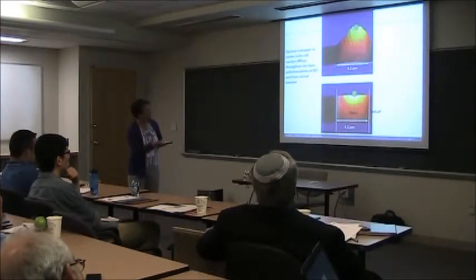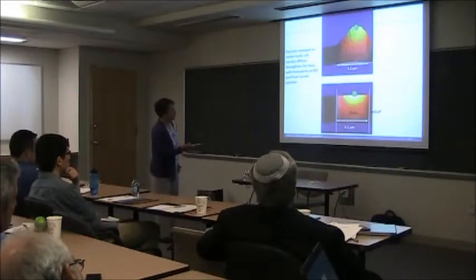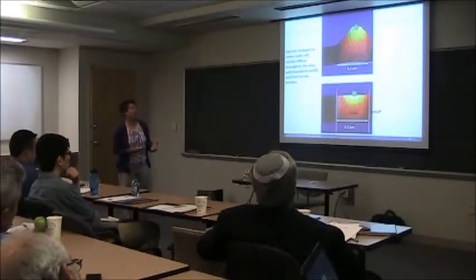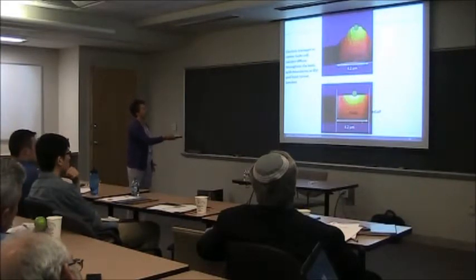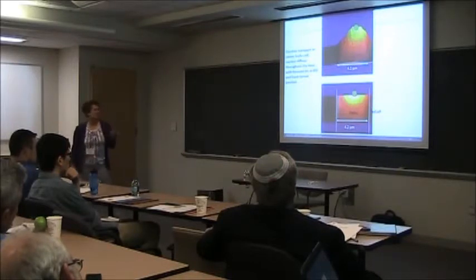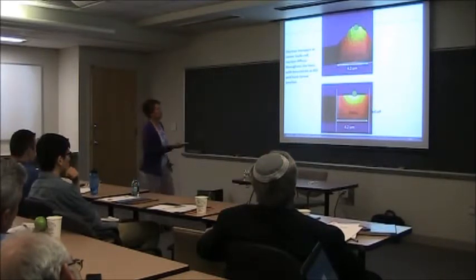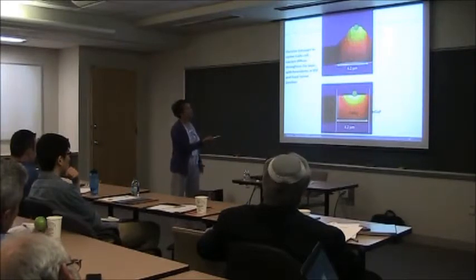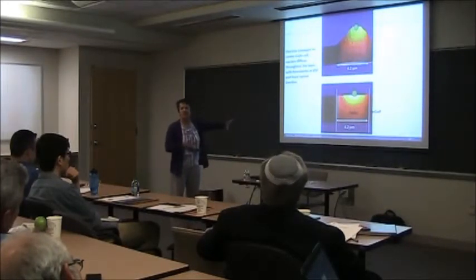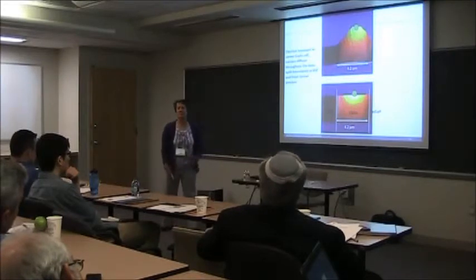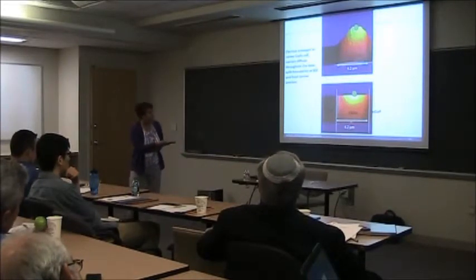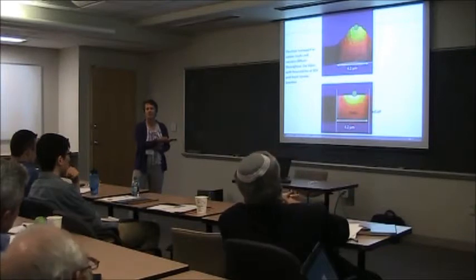So this is the same data in 2D and in 3D. Again, the electron beam is here, okay, at a point. And when I scan, you see that I get luminescence, again, due to carrier transport, through this entire gallium arsenide layer, bounded by the tunnel junctions. And that means, of course, that the solar cell is doing exactly what a solar cell should do. These are high-quality materials. Carriers are diffusing throughout that whole area, making it to the junction, and some fraction of them, however, are recombining along the way.